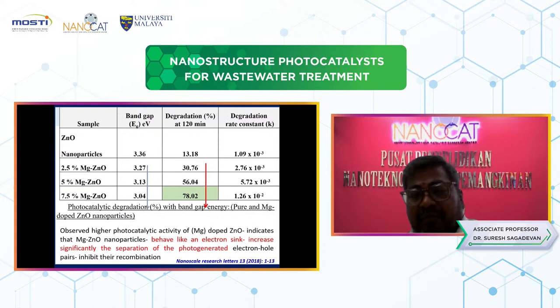Why is it only shown for 7.5%? Because what happened with more than that doping percentage? We tried different mole percentages more than 7.5. We tried 10 also, but it was observed that with the lapse of time, the peak intensity decreases, indicating the greater degradation of rhodamine B due to the photocatalytic activity of zinc oxide, and also due to the presence of defects and oxygen vacancies created by Mg doping inside the zinc oxide matrix.